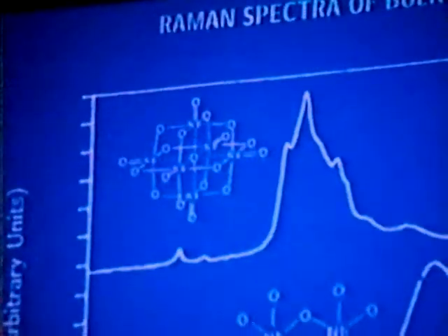This is the well-known structure of the Nb6O19. We can see there are 6 terminal niobium-oxygen double bonds, whose Raman band appears around 870. They also have many niobium-oxygen-niobium bonds, whose Raman band appears at 530. And there is an associated bending mode in the low wave number region.